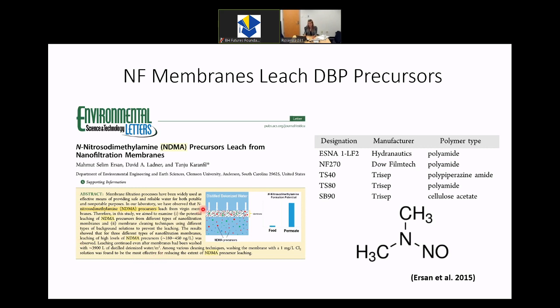So they basically, and you can see the visual here, they put distilled deionized water through, so laboratory grade water, ultra pure water through the membrane. And they then take samples of the permeate, so the other side of the membrane, to see if there's something coming off of the membrane itself. But because you don't know what you're looking for, that's typically pretty difficult.